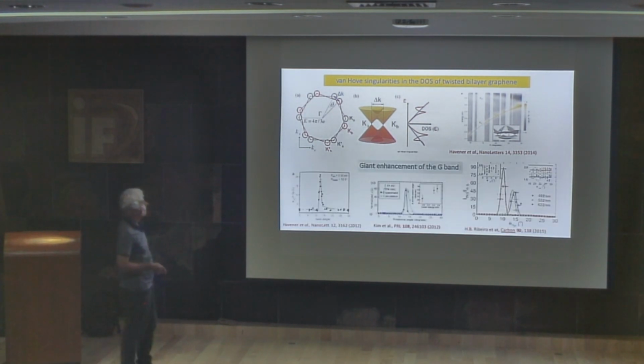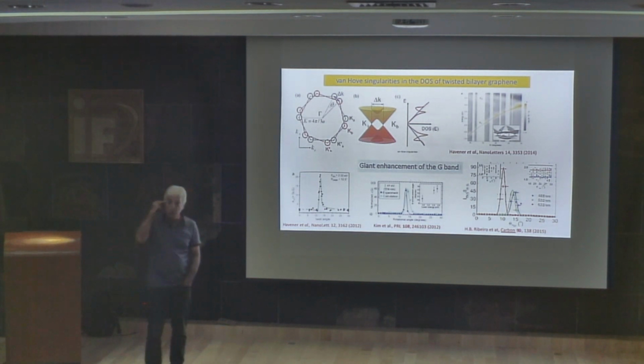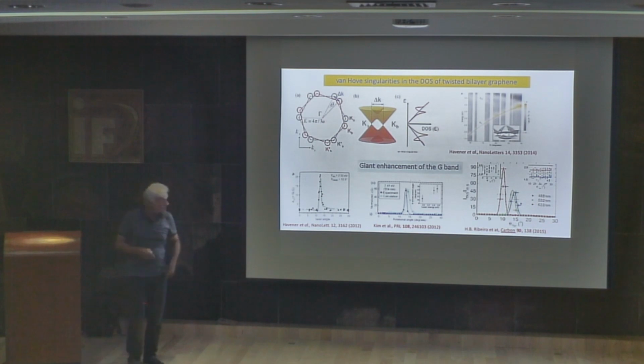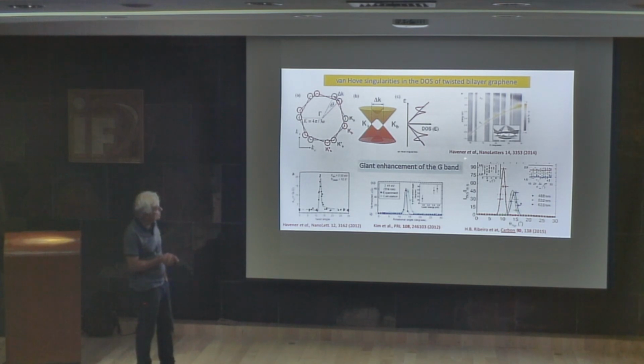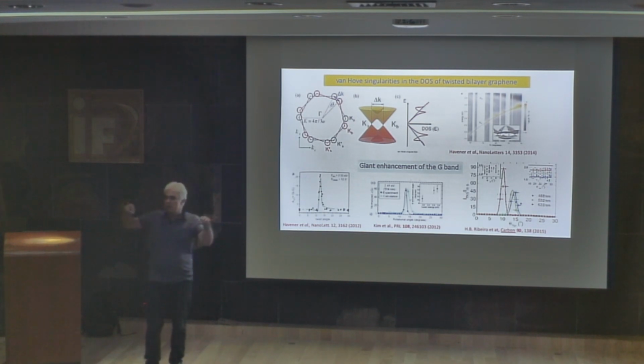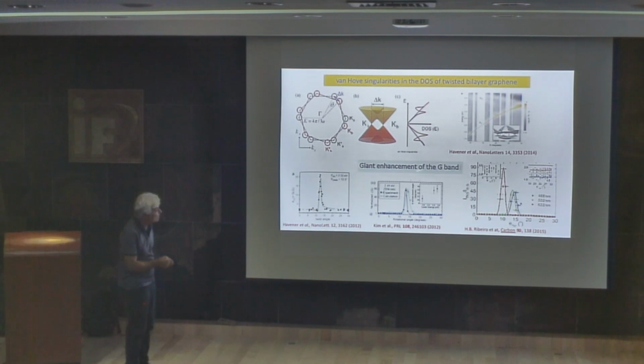Then one thing that was realized in those three papers is that if I'm lucky to have one laser that is in resonance with those singularities, then we have the resonant Raman condition. Then the intensity of the peaks becomes very, very intense. For example, in this case, the intensity of two layers divided by the intensity of one layer. Normally, we would expect about two times, because I have two layers, but in this case you can see that the signal can be 90 times stronger.